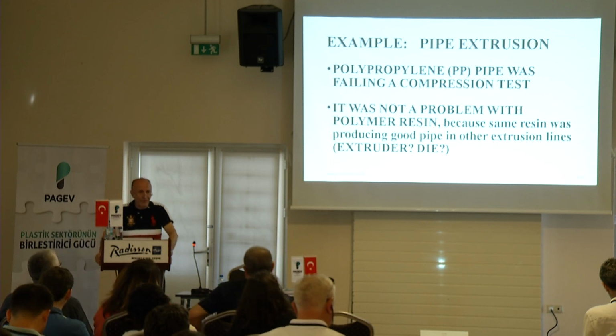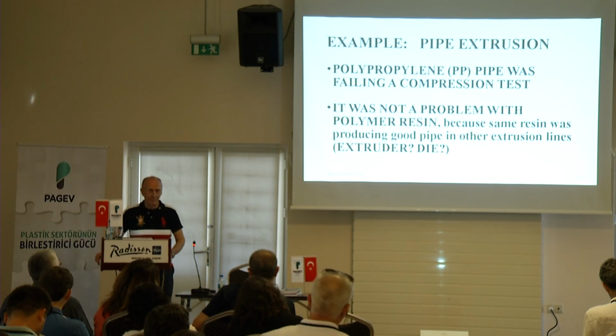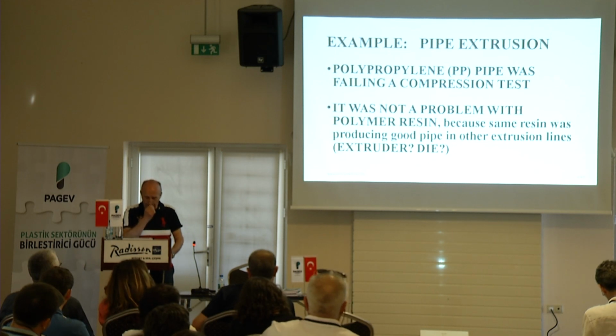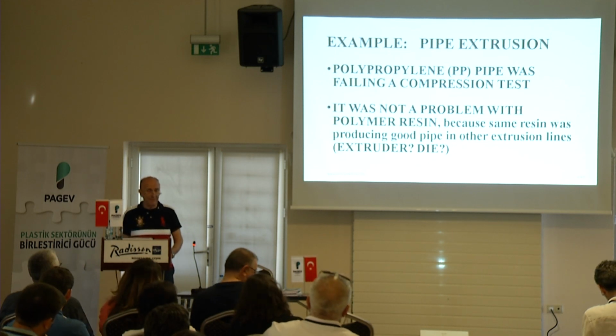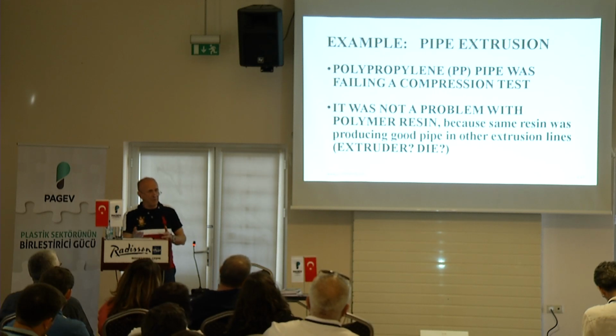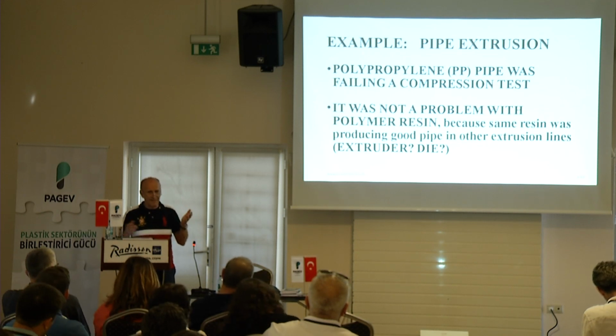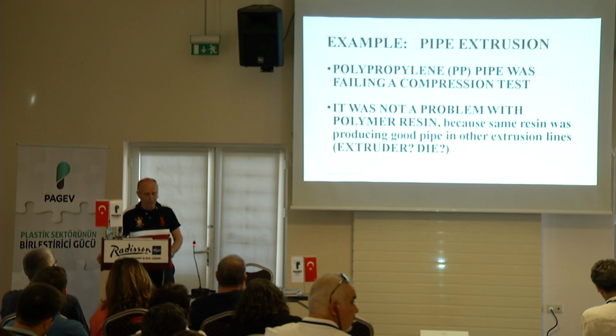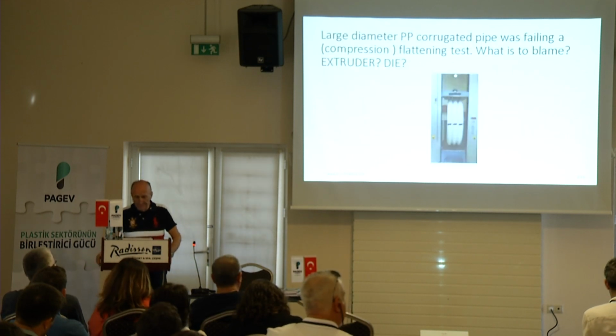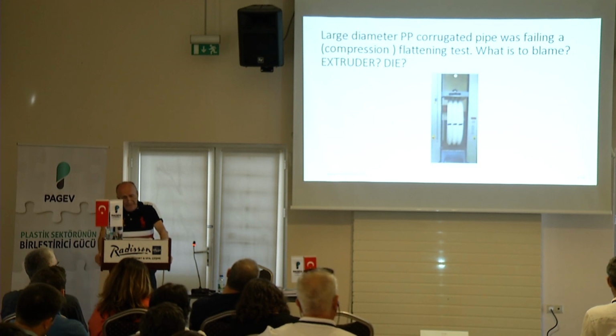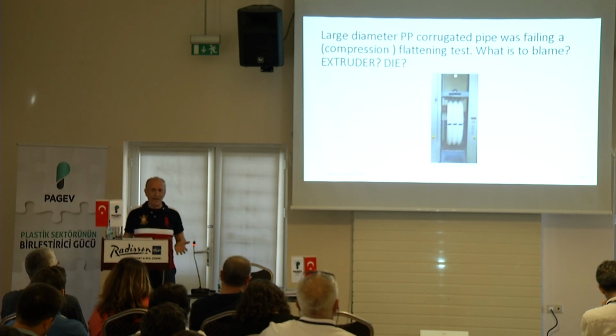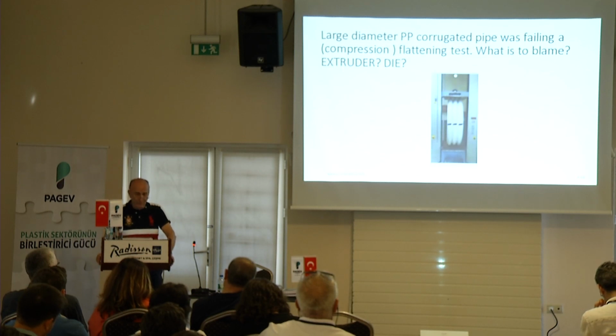We were trying to figure out where the material was coming from. We thought in the beginning that it was a problem with the resin. We took the resin and measured viscosity and tensile testing, and it passed all our university tests. However, in the plant test, a compression test according to an ASTM standard, it would fail. Question is why?